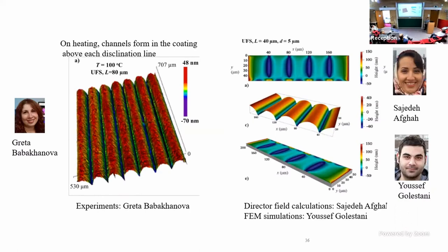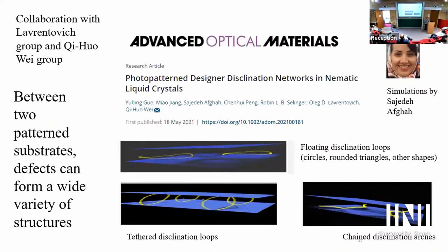I should also say Sajedeh Afghah, who now works at Intel, did the modeling of the microstructure so we could figure out where the disclinations were and what the director field should be. And Sajedeh also did some beautiful simulations just of all different kinds of antagonistic boundary conditions. And we can make disclination lines that are like smoke rings that sit in the middle, not touching the top or the bottom, or they can be tethered to the top and the bottom,